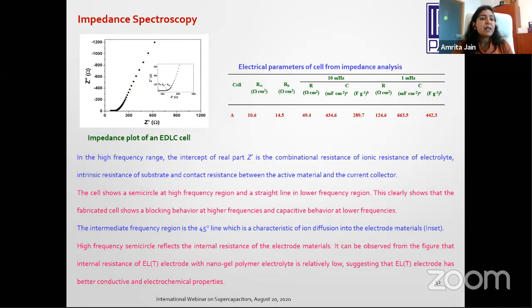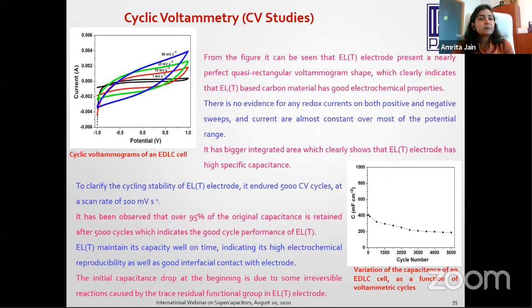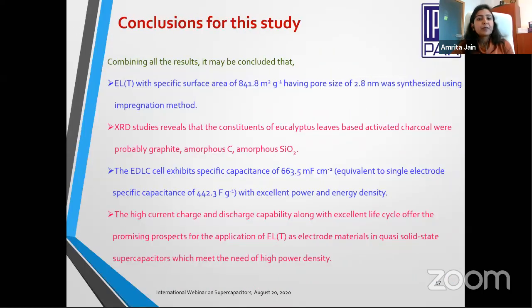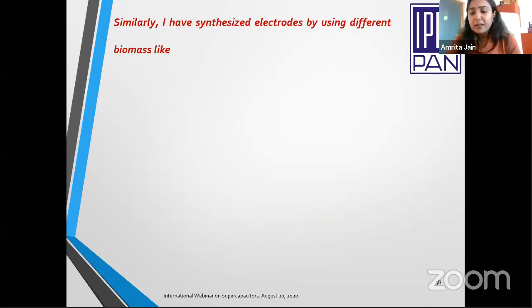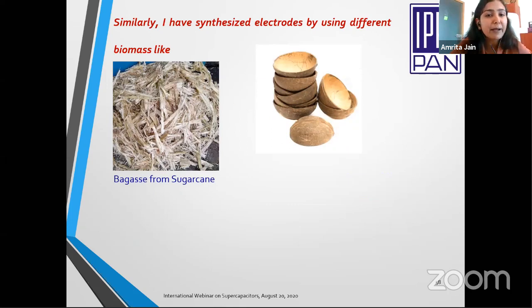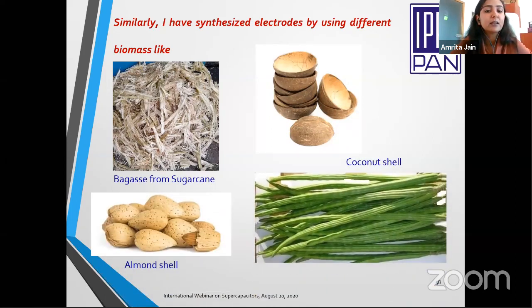Then impedance spectroscopy plots, and the capacitance value is as high as 434.6 millifarad per square centimeter, equivalent to 289.7 farad per gram. Complex power analysis, CV studies. This is cyclic voltammetry, and this is the cycle number. We have performed 5,000 cycles. Charge discharge measurements. Similarly, I have used many biomasses like bagasse, coconut shell, almond shells, some drumsticks, and still I am using a few. I can't share because the results are still not published and are under work. So these are all waste materials, and we have achieved really nice results from them.